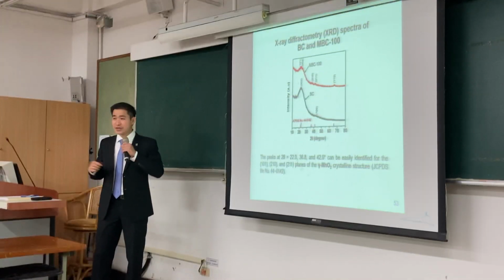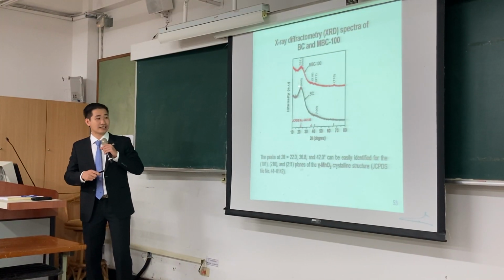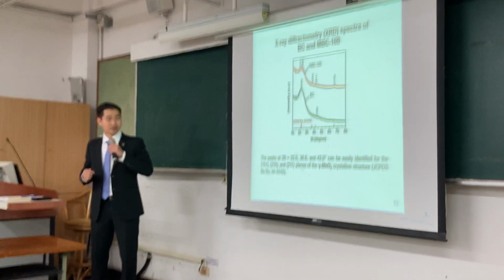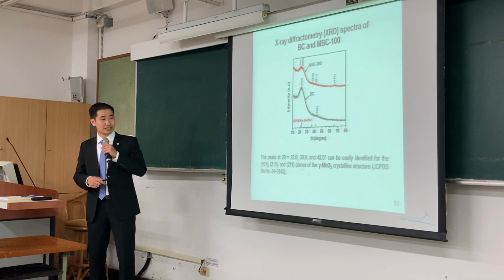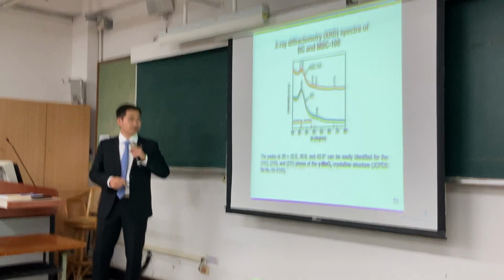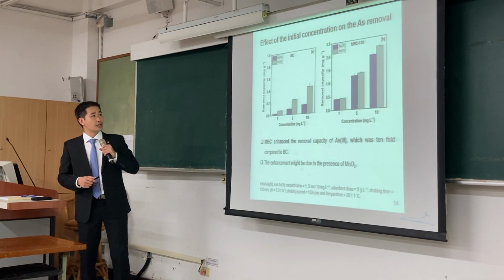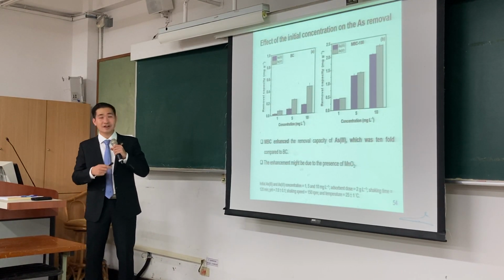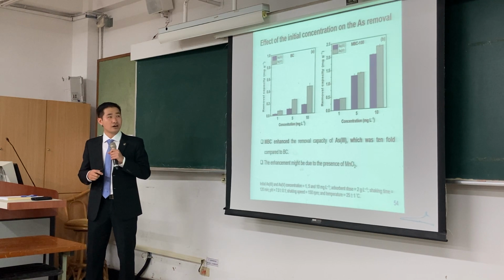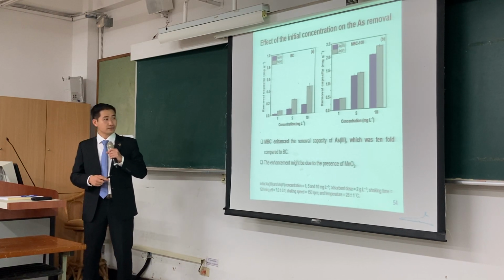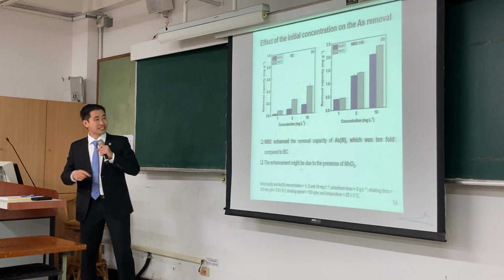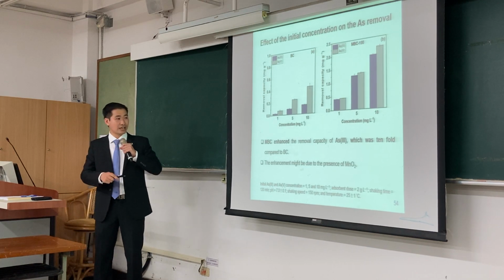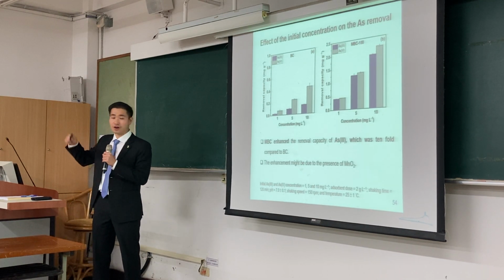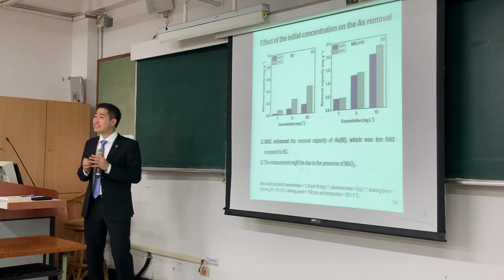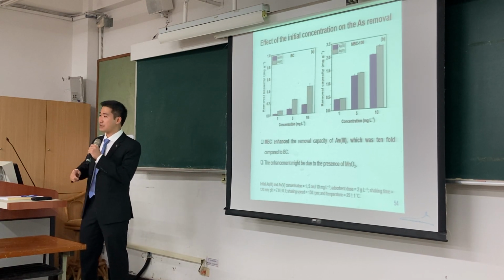The XRD spectra identify the gamma manganese dioxide crystallized structure. More interestingly, regarding the effect of initial concentration on arsenic removal, we can see MBC enhances the removal capacity of arsenic 3, which is tenfold compared to BC. The enhancement may be due to the coating of manganese dioxide.